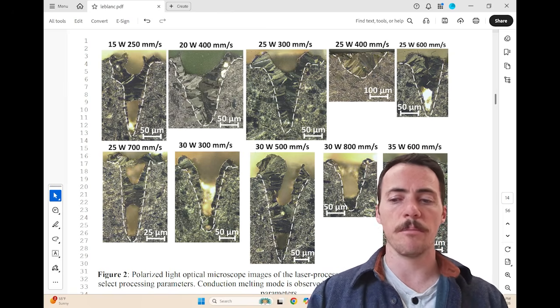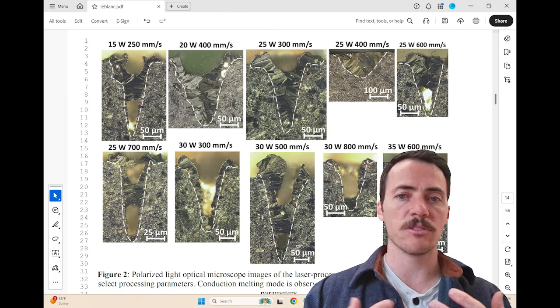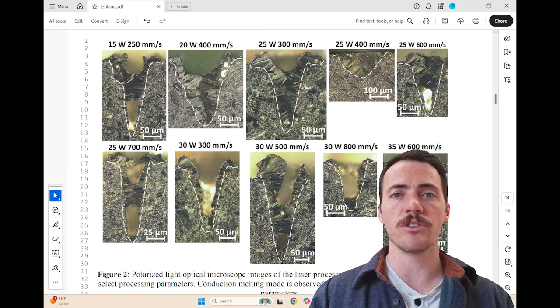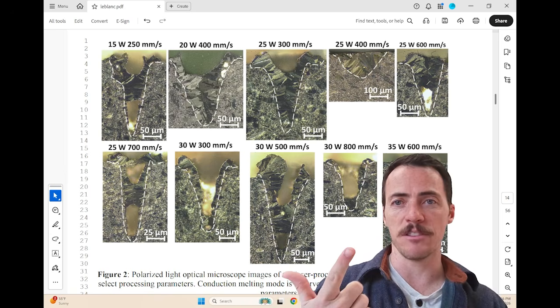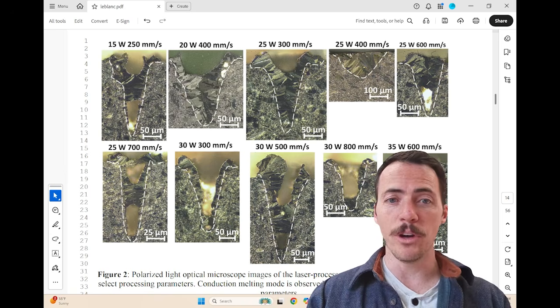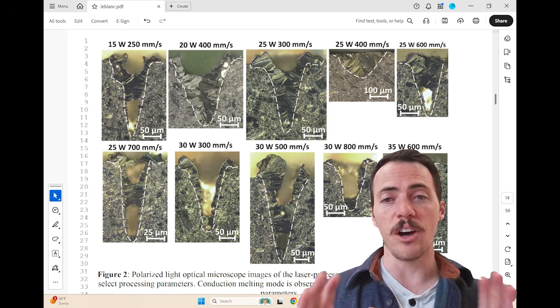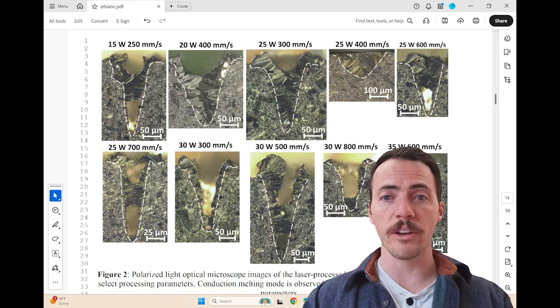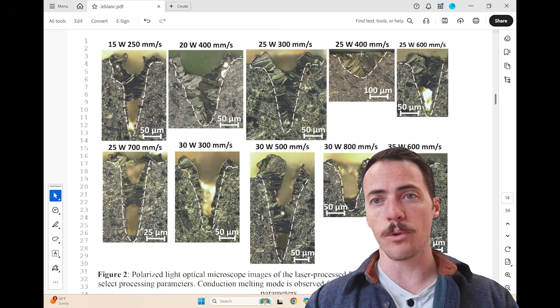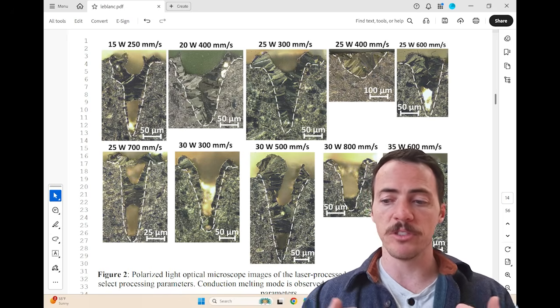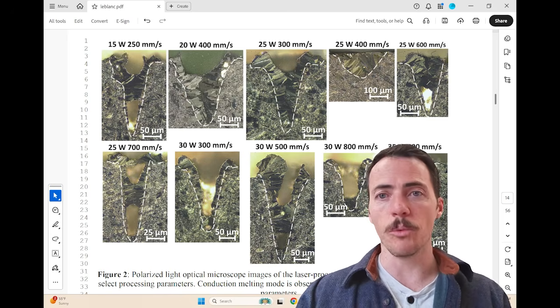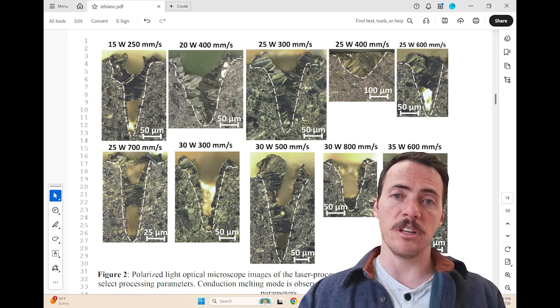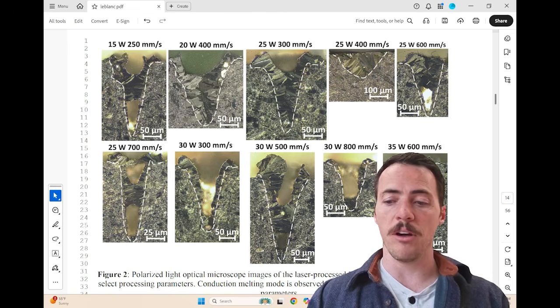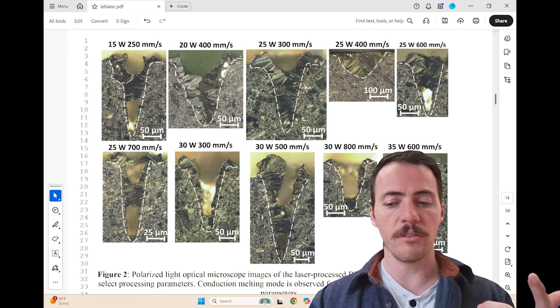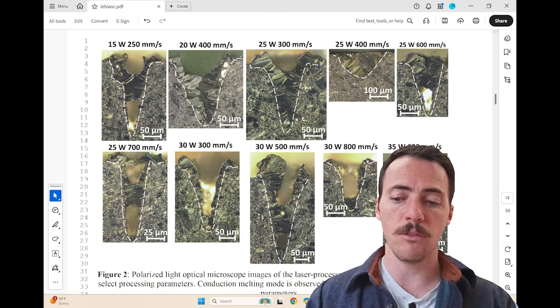What you see here is a bunch of different microstructures where you're looking at sort of the melt pool conditions as a function of laser power and the scan speed, just 2 parameters, right? And what do you notice here is that there are a lot of problems. In fact, only one of these 10 right here at 25 watts, 400 millimeters per second, produces the sort of stable processing window that you would expect to see, similar to like what you see in metals. All the others are dominated by all sorts of problems. You've got Marangoni convection, you've got lots of keyhole formation.